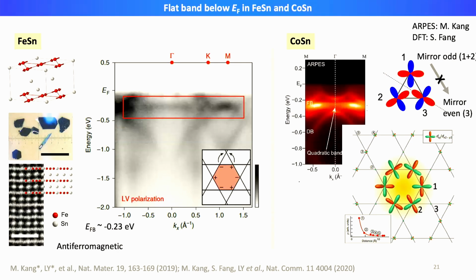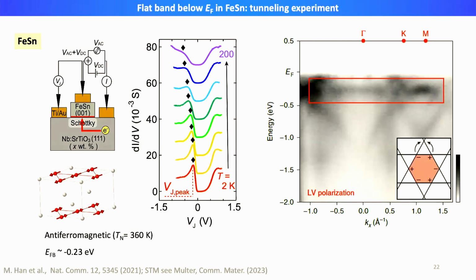So not only are we able to see these flat electronic states from photoemission, here I want to show you a result of tunneling spectroscopy through one of the flat band hosting materials, iron tin. In this particular case, we were tunneling between a semiconducting substrate and the metallic thin films. The dI/dV as a function of voltage can be used as a proxy for the density of states as a function of energy. We can see that there is indeed a peak in the density of states around the same energy where you see the flat band in the photoemission.